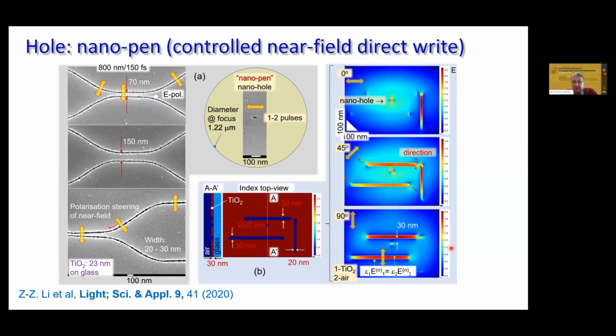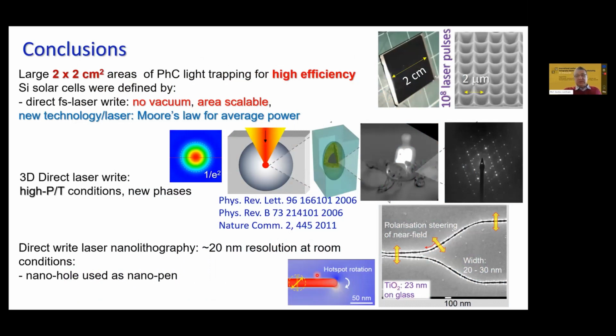writing on dielectric films in a way as we are working with electron beam lithography and polymeric resist. And also one important feature is that this type of writing can also be done on curved surfaces because there is no limitation. And this is done simply by focusing your femtosecond laser and very good control of positioning. That's it. So this brings me to conclusions.